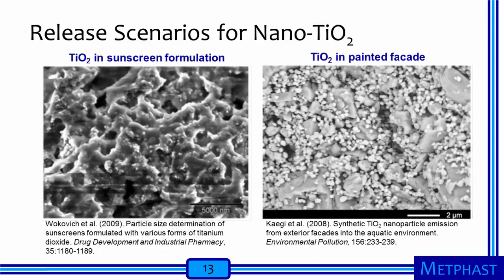Titanium dioxide nanoparticles are used in products that may release the nanoparticles into the natural environment. The image on the left from Wokovich and co-authors shows a scanning electron microscope image of a sunscreen containing nanotitanium dioxide. The sunscreen was dried in a vacuum. The image shows that most of the titanium dioxide nanoparticles have agglomerated to form larger clusters. After people apply sunscreen, they may swim in surface waters and will later shower or bathe, releasing these agglomerated nanoparticles directly into surface waters and wastewater.